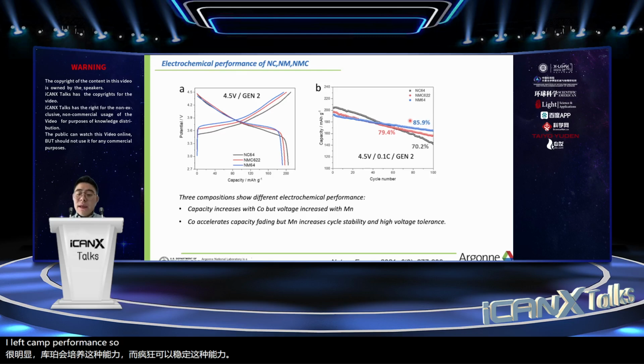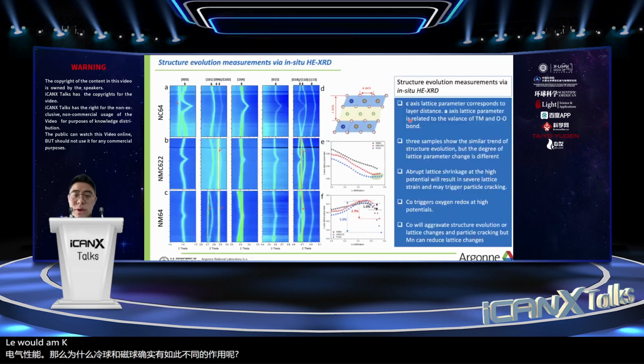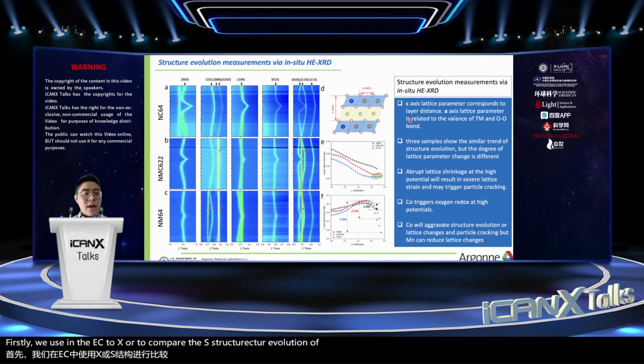So why do cobalt and manganese have such different roles in the layered NMC cathode materials? So to understand the mechanism, we are using many techniques to evaluate these three materials. Firstly, we're using the in situ XRD to compare the structure evolution of three cathode materials. So in general, these three materials show very similar structure change processes.